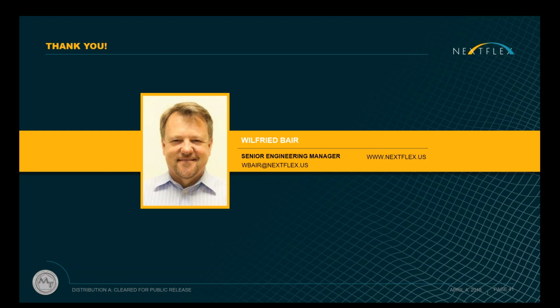But we have done qualification of pick and place of ultra-thin die on our die bonder, and we can do 50 micron quite readily and very high yielding. And we are right now in the process of qualifying a 30 micron die process.